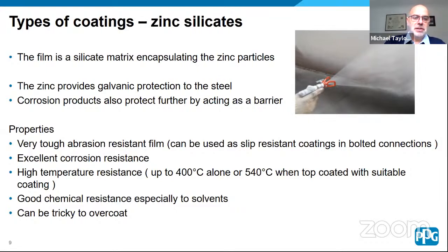Zinc silicates give excellent corrosion protection, but they also give high temperature resistance as well, up to about 400 degrees if it's just a zinc silicate coating on its own, or you can top coat them with something like a silicone, and you'll get up to 540 degrees. So you can imagine if you use it on the outside of a chimney, for example, you could use the zinc silicate and then overcoat with a silicone in a particular colour. We see quite a few of the red, white chimneys around. That's typically what this system could be used for.